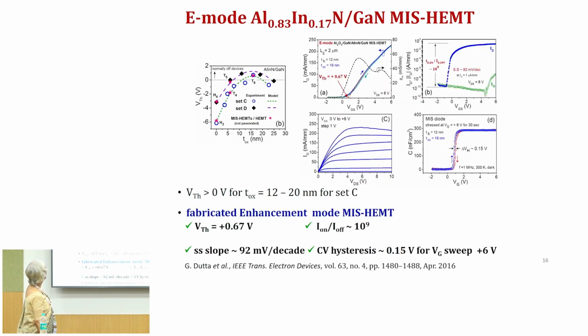So, again here we were able to obtain enhancement mode aluminum indium nitride gallium nitride MISHEMT, these are the characteristics. We were able to obtain a threshold voltage of plus 0.67 volt with very good Ion by Ioff ratio. These are of course much larger devices. Here the gate length is about 2 micrometer.